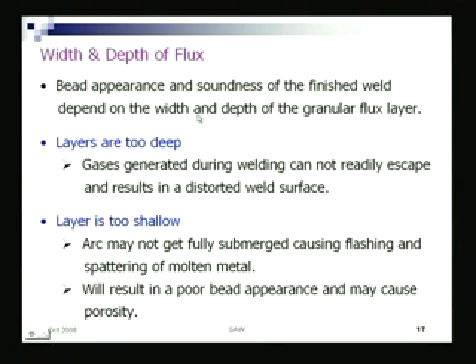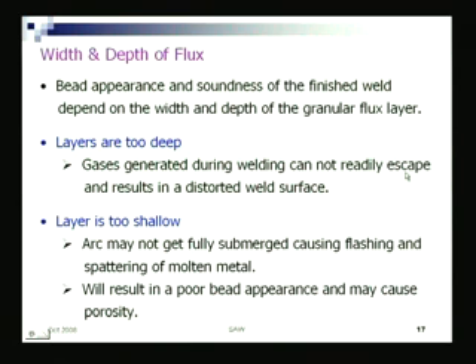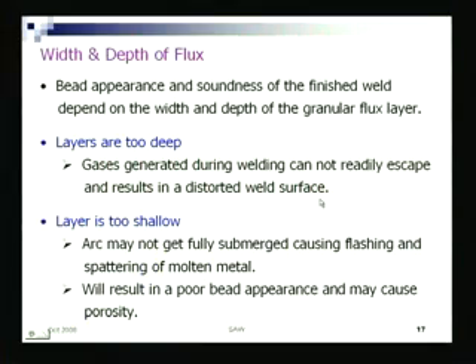Width and depth of flux, bead appearance and soundness of the finished weld also depends on this width and depth. If the layer is too deep, too much flux has been poured, the hopper position is not fixed or aligned properly, so too much flux pours over the weld deposit, then gases generated during welding cannot readily escape, and the molten slag will be under pressure from the weight of the flux. So we will get a distorted weld surface.